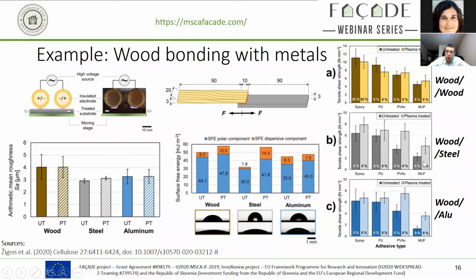One very notable one is on the aluminum substrate. We find that, with the exception of the melamine urea formaldehyde, all other three adhesive systems perform better than the best non-plasma treated sample did. But also, even the relatively simple water dispersion based PVAC adhesive performed better than the epoxy adhesive system usually utilized for this application. This kind of improvement for the PVAC is something particularly interesting to look at in the future.